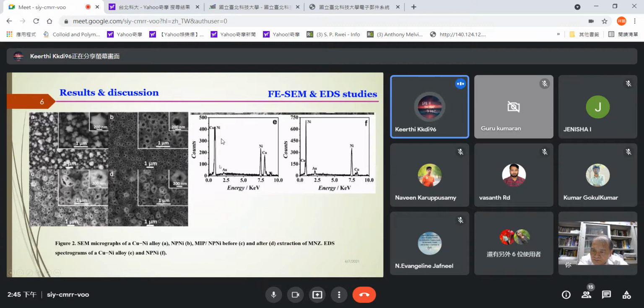The EDX spectrum clearly shows a decreased intensity after removal of the copper from the electrode, indicating the successful removal of copper from the surface. It's also evidence of the efficient result.